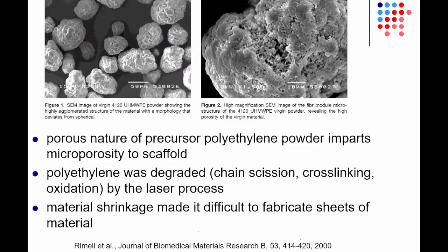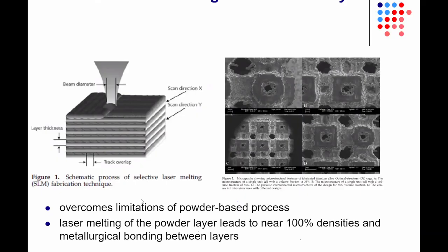You can see here examples of ultra high molecular weight polyethylene powder being used, and you can see here that in fact this is a challenge because you're having CO2 laser interaction with the material that can cause degradation of the polyethylene. You have chain scission, cross-linking, and oxidation. The porous nature of the precursor polyethylene powder imparts microporosity to the scaffold, which can be a benefit, but at the same time, you can have difficulty in terms of creating sheets of the material because of material shrinkage.